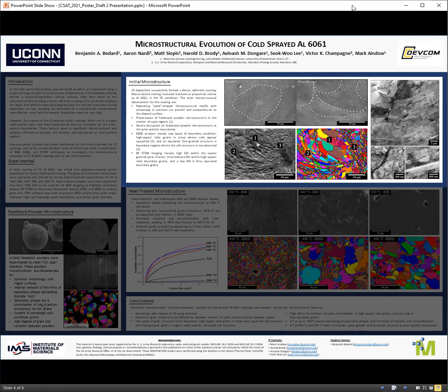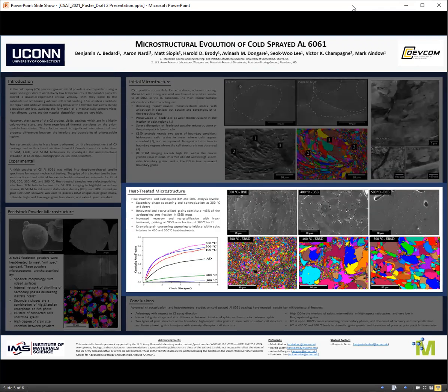This deformation manifests in two microstructures: a squashed cell structure, where cells and grains appear to have been pancaked during deposition, and a recrystallized structure where cells are not readily observed, but fine equiaxed grains are revealed in EBSD mapping. Bright field STEM imaging has been used to observe the dislocation density of these different regions. It can be seen that the interiors of prior particles exhibit high dislocation densities, and boundary regions show evidence of dislocation-free, yet equiaxed grains. After heat treatment, three main microstructural evolutions are observed.